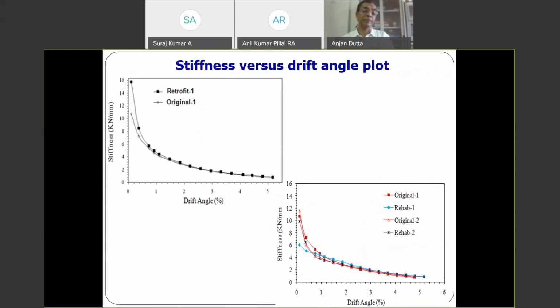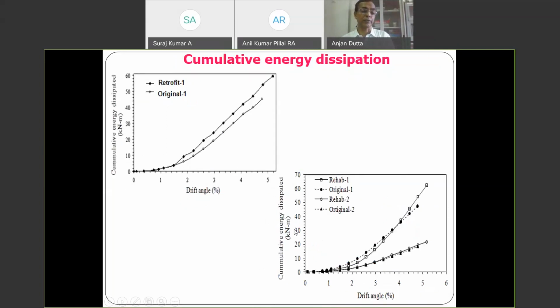And you also look at how the stiffness is changing as you go on increasing the displacement level. So with higher and higher drift, more and more damage will come in. So there will be degradation in stiffness, and this is what you can look at. And one more important thing which we look at is the plot of energy dissipation, because this is the measure of your seismic power, a very important requirement for ductility. So you can see that your original specimen, if this is the cumulative energy, your retrofitted specimen is having a higher energy level. That means it can now dissipate more energy than the control specimen. And similarly, all your rehabilitated specimens are more or less similar to the original specimen.